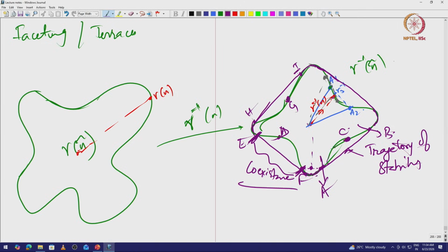But whereas if I have J here, J is a stable surface. Okay. So, these lines that are outside this plot define the coexistence of this plane and this plane in different areal fractions, right. So, essentially if there is a plane here, that will eventually split up into E and F, that is the global stability. Okay.